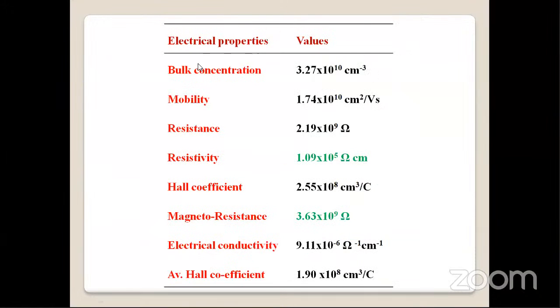So these are the electrical properties I got as results from the Hall effect system: bulk concentration, mobility, resistance, resistivity, Hall coefficient, magnetoresistance, electrical conductivity, and average Hall coefficient. The important parameter is resistance. This resistance is 2.19 × 10^9 ohm. In terms of resistivity, it is 1.09 × 10^5 ohm centimeter. This is in Siemens. Then magnetoresistance. These two are very important.